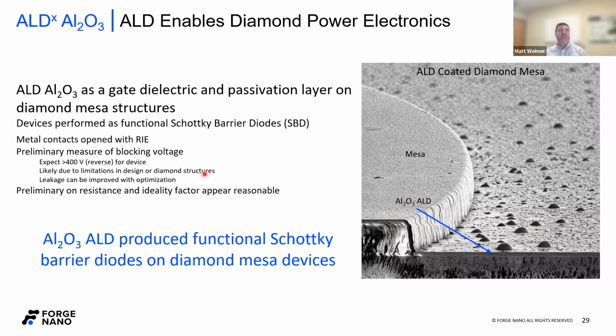I think here is where we have to think again about what those interface defect sites actually look like, especially after etch, and what we can do to clean that up. So, again, the parameters of the device, resistance and ideality factor, seemed reasonable, but it wasn't anything mind-blowing yet. But I was still really proud that we were able to get functional diodes.